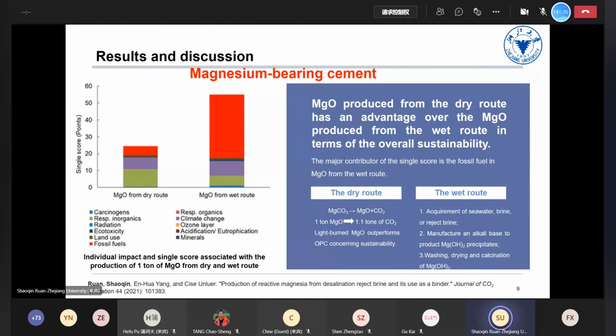And the second part is about the wet route. The wet route obtains MgO from seawater, brine, or rejected brine. You need some alkaline bases to produce magnesium hydroxide first. Then you calcinate these products to produce the MgO. But from our experiment, we find that the MgO produced from the dry route has an advantage over the MgO produced from the wet route in terms of overall sustainability.